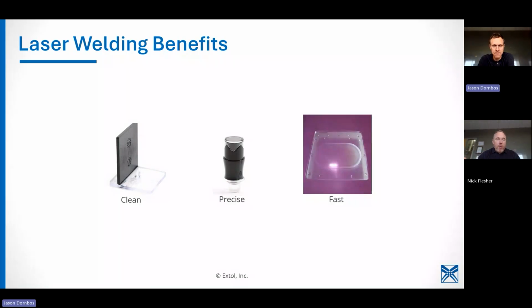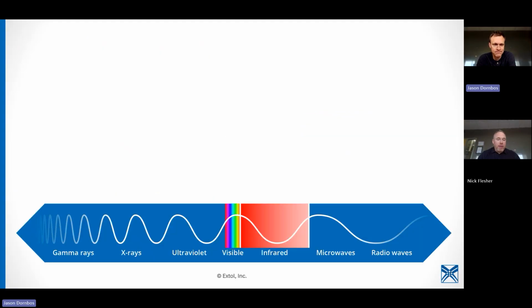From a precision standpoint, we've talked about 0.7, 0.5 millimeter. Typically, our weld ribs are 2 to 3 millimeters. This part that you see in the middle was less than the diameter of a dime. We've even done smaller. And I think our collapse on that was 0.1 millimeters. So that's the level of precision you have in energy into the plastic, which is really tough to do with ultrasonics. Once that plastic gets going, it just wants to go. Hot plate welding can be quite precise, but those are the three benefits that we typically see.